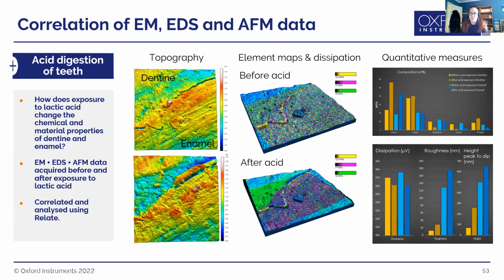And we did the EDS first, we took it to an AFM, we did the AFM measurements while it was being digested with acid, and then took it back to the EM. So there's lots of back and forth. This was during lockdowns, involved shipping samples around the country. But we were able to get some really nice data and distributions.